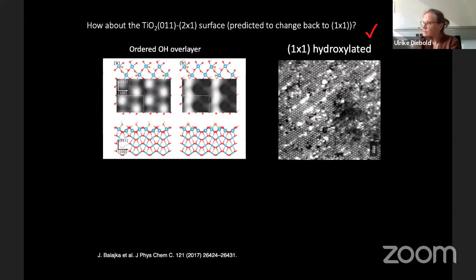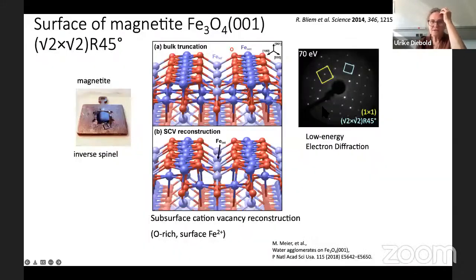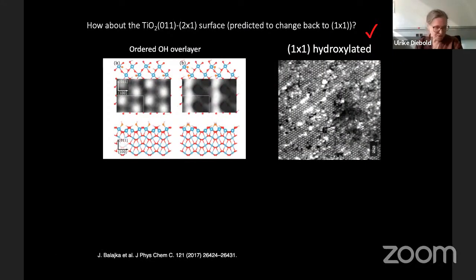But when you do it under well-controlled atmospheres, then actually you can make STM images before and after. So this is this 011 surface, where the first principle molecular dynamics calculations I showed you a little bit earlier predicted the surface would change back to bulk terminated 1 by 1, and in fact it did. So that's what we do right now. We do different things in my group. One is we really try to make hydroxyls and measure them with our non-contact AFM, but we also want to see how realistic these surface structures are.